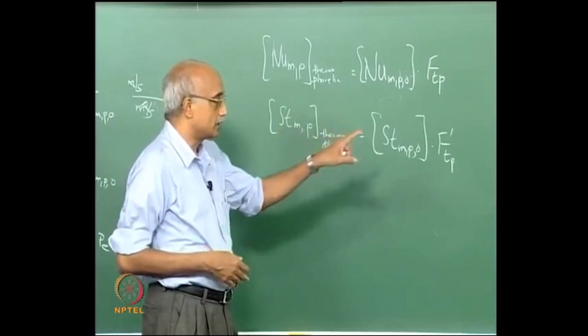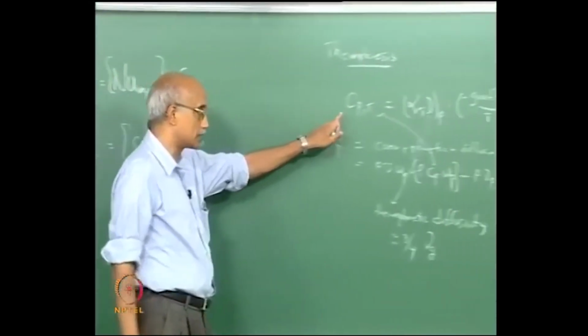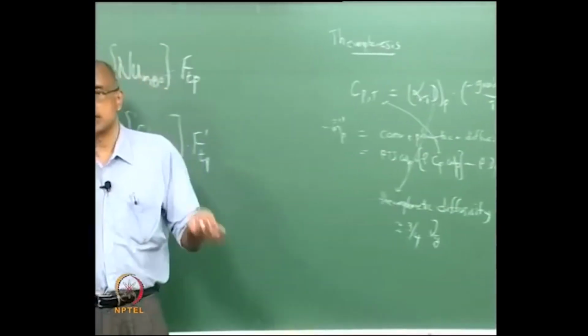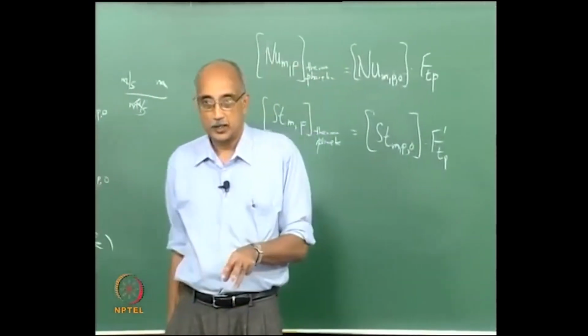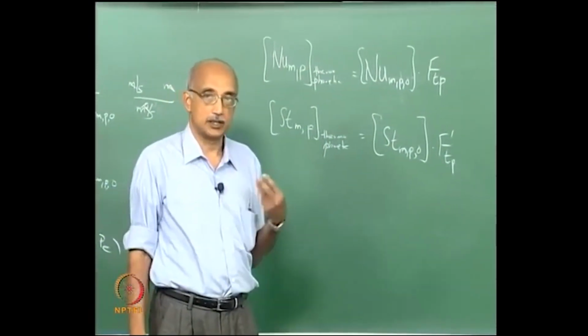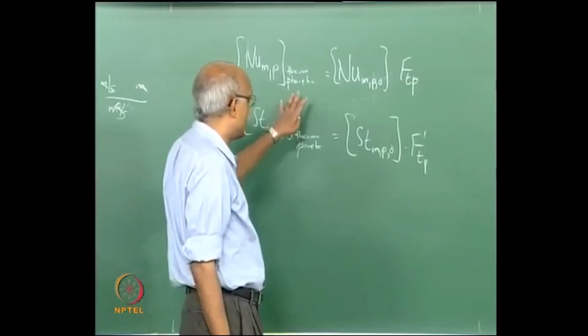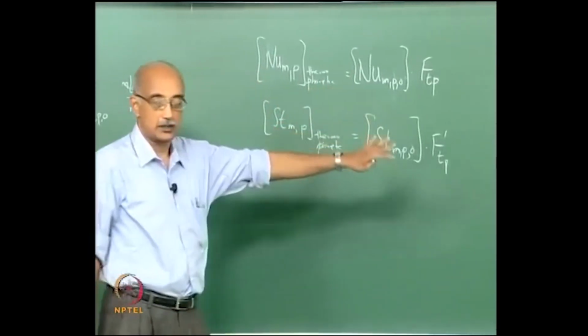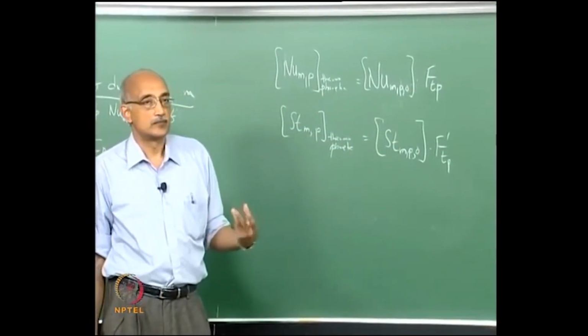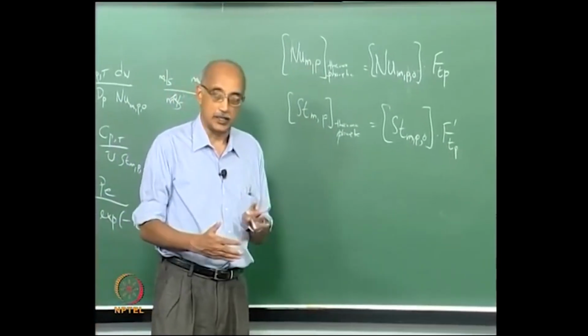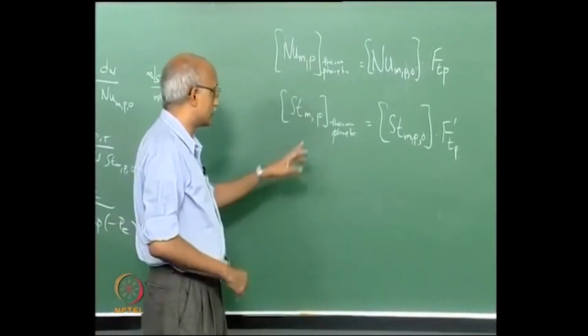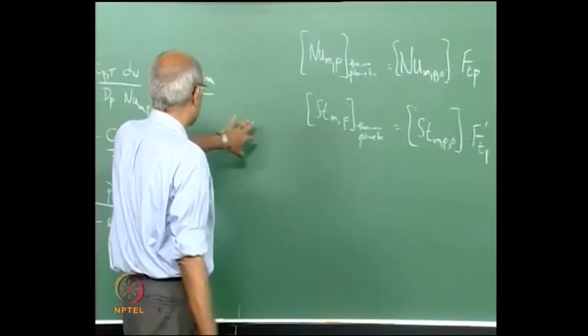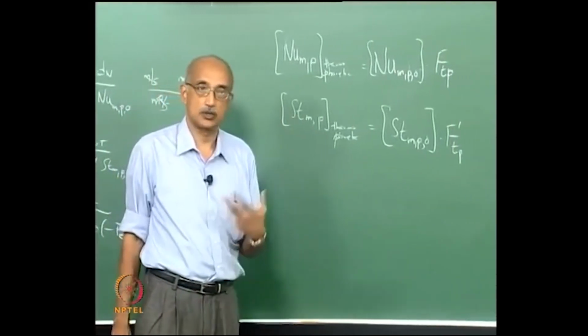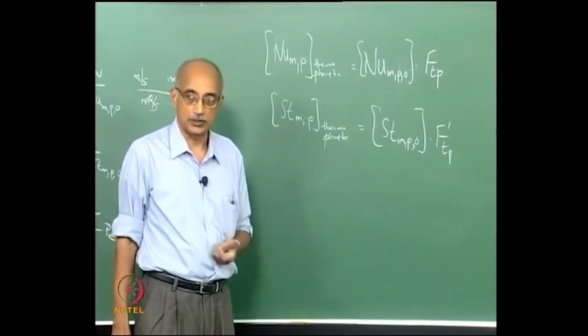So we estimated the corresponding phoretic velocity. From the phoretic velocity you estimate the Peclet number, from the Peclet number you estimate the correction factor, you apply the correction factor to the baseline Nusselt number or Stanton number to obtain the actual prevailing Nusselt number and Stanton number, and then again you multiply these with the reference fluxes to obtain the actual flux that is going on.